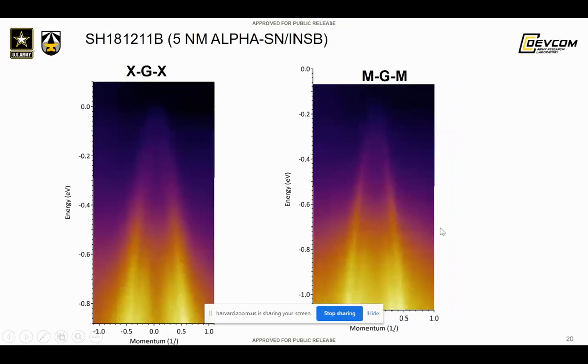If we go to a smaller thickness, this is interesting. We see evidence that this is actually 50 angstrom thick. We see evidence that the Dirac cone is still quite evident, or at least close to it anyway. We don't see the evidence of the band hybridization because it's slightly above the gamma-8 band states. So we don't see those tails due to the heavy hole states.